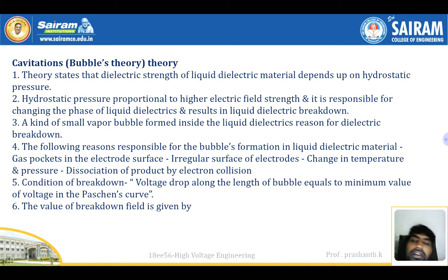See, it depends upon everything. How do you reduce the breakdown strength of liquid materials? If dust particles, moisture content, bubbles or other impurities are present, the breakdown strength also decreases, right? Even though hydrostatic pressure is proportional to higher electric field strength, small vapor bubbles formed inside the liquid dielectric are a reason for dielectric breakdown. If small vapor bubbles occur, right?